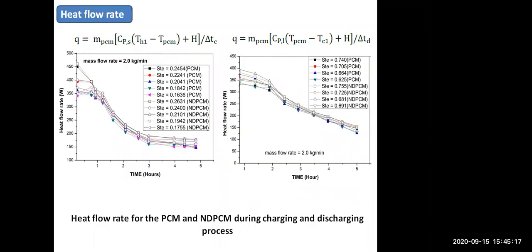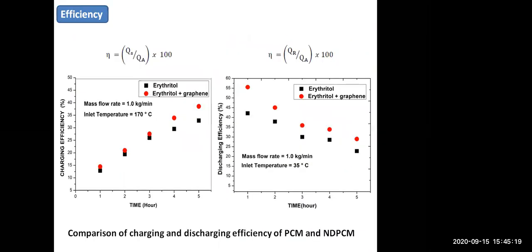Then efficiency. The charging efficiency of the system was increased by 32.8% for PCM and 42.87% for erythritol with graphene. The discharging efficiency of the system was 38.25% for PCM and 55.08% for NDPCM. The efficiency of the NDPCM is higher than the PCM, which is due to the dispersion of graphene nanoparticles in the erythritol PCM.